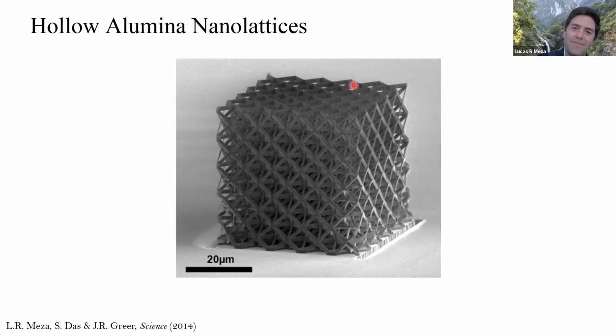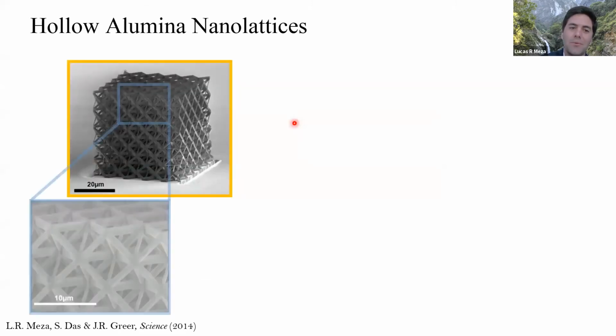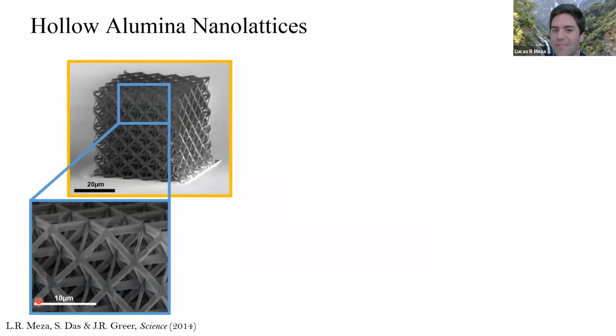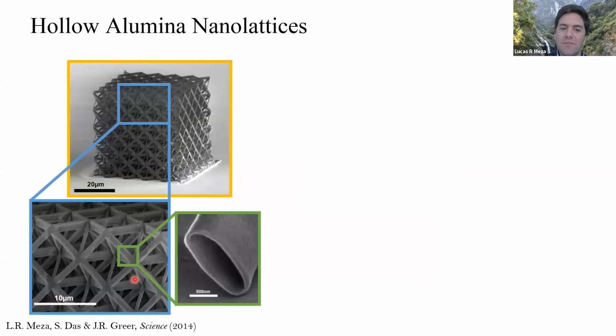So 50 microns total structure. These are built with unit cells that are on the order of 5 to 10 microns. And then at the smallest level, these are hollow tubes with thicknesses on the order of 10 to 100 nanometers, which we can control pretty well.